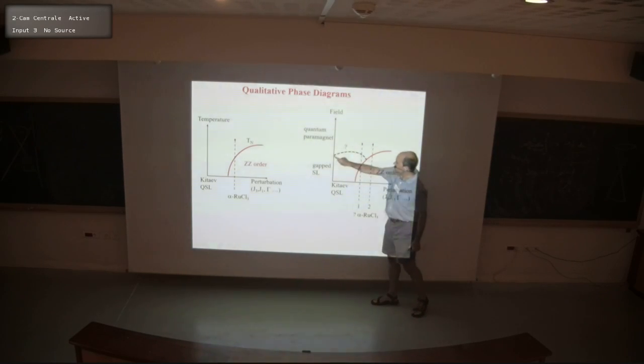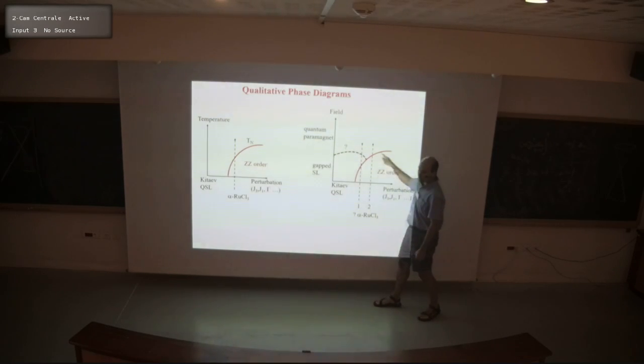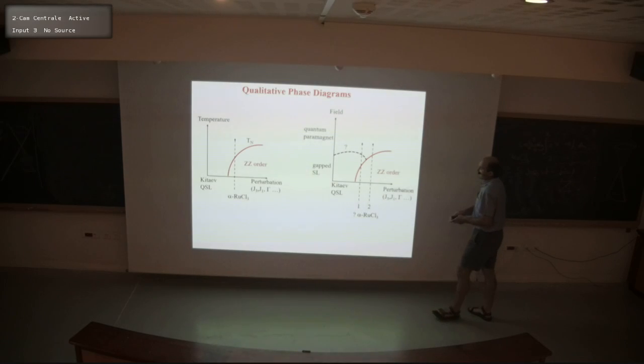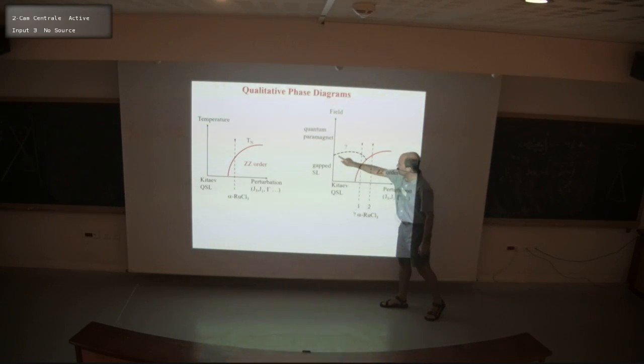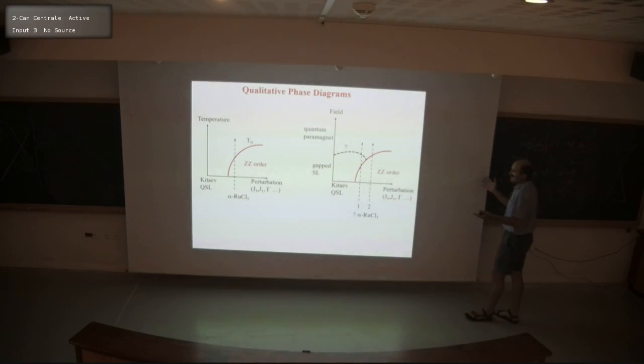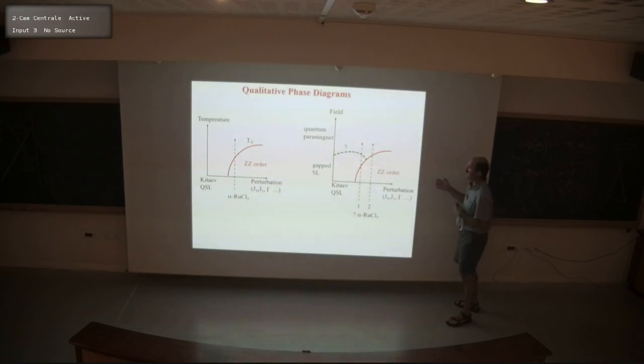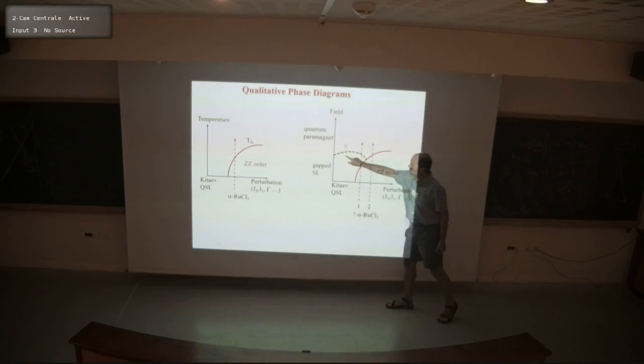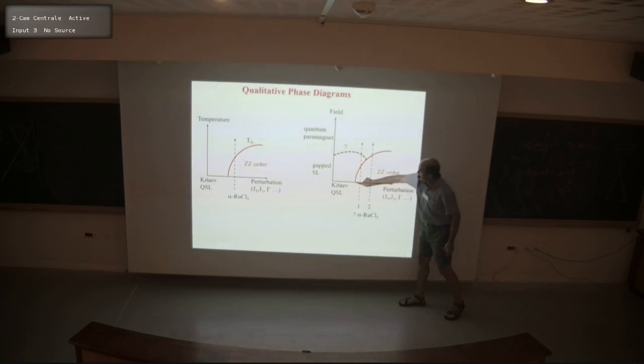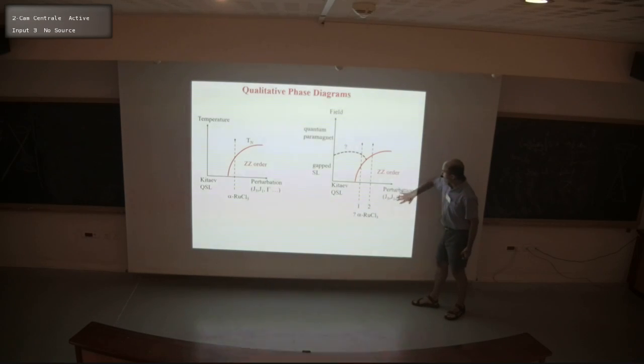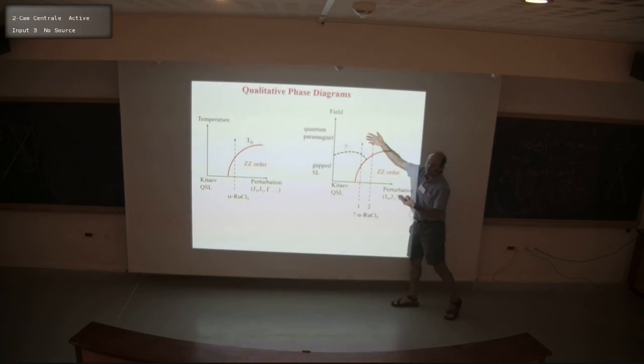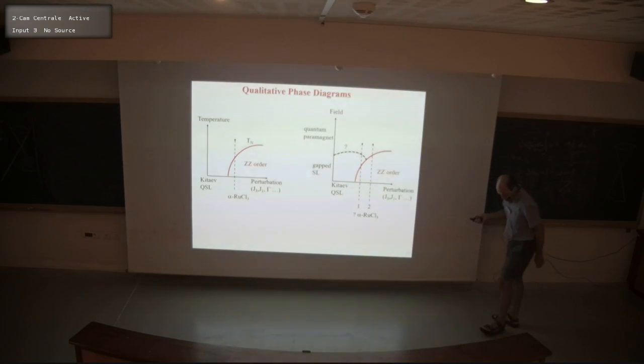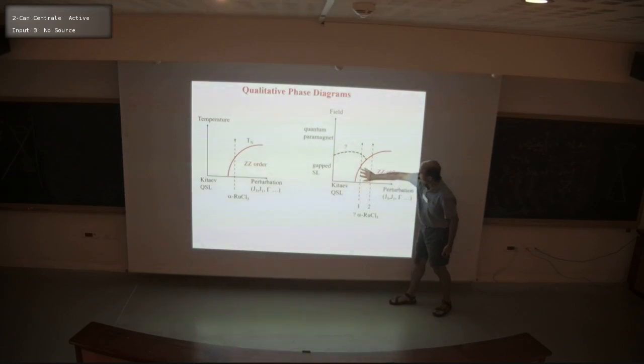Now, anchored on this point, there must be a phase boundary that somehow crosses the phase diagram. Depending on the different perturbations, there are various scenarios where this phase boundary may have different behaviors. Just to fix ideas and explore something that's discussed in the community, let's imagine a scenario where the phase diagram looks something like this phase boundary. This has to increase this way because as we put in more perturbation, we strengthen the zigzag order, so we need a higher field to suppress it. Now the question is, starting from this scenario, whether the experiments are in a region where you go from the zigzag order into the gapped spin liquid phase and then to the quantum paramagnet, or whether you suppress the zigzag order and go straight here.